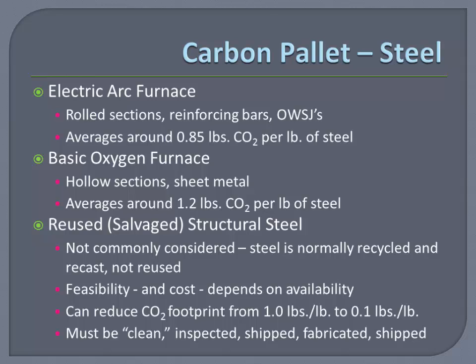In a real nutshell, there's a couple of different kinds of manufacturing of structural steel. Electric arc furnace in this country is the most predominant way to produce rolled sections. It's essentially the only way that's effectively being done anymore in this country, but there are basic oxygen furnaces around the world that produce rolled sections that have a higher carbon footprint. So averaging 0.0, 0.85, and 1.2 comes out to be somewhere around a pound. Okay, for general purposes, you emit about a pound of carbon dioxide into the atmosphere for every pound of structural steel fabricated and erected. That includes the incidental erection footprint.